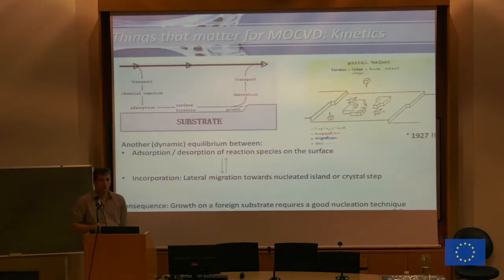Another important aspect, I'm slowly building up to some movies that will make everything clear, but I need to explain it like this first, is the kinetics of the MOCVD growth. And again, there you have an equilibrium between particles that reach your surface, you have migration across the surface, and then you have competition between either desorption, where you lose the precursor, or incorporation in the crystal, which typically happens at a step, so at the edge of an atomic step. This can either be because your crystal has some off orientation and you have natural steps on the surface, or it can be in these islands, these nucleation islands that you have already formed before.